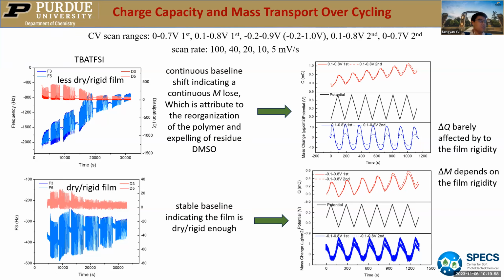One thing for the less dry and less rigid film is that we can see a baseline shift. It tells us the film is continuously losing mass. What's the reason? Because the film is not rigid enough. During electrochemical cycling, it keeps losing mass because of the reorganization of the polymer and maybe the expelling of the residue, DMSO. But when we have a very dry and rigid film, we have stable cycle performance.